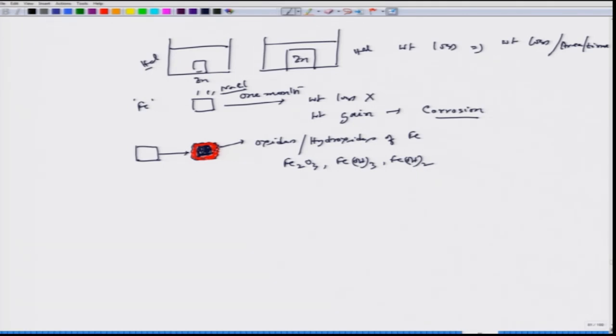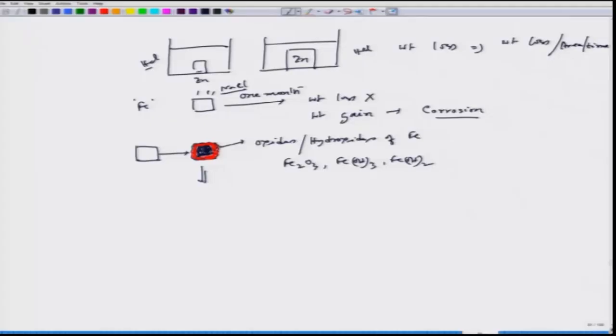In those cases, you have to carefully remove the oxide layer or the surface layer, and that removal should be done so carefully that the inner part, which is the metal part, should not get damaged or should not get removed. So that is what we have some standards, how to remove the oxide layer, which is mostly done chemically, and then after removal, we are left with this much small piece, and that one we have to take the weight. So this is W2 and here the weight was W1. Now, and this one is W prime. So W prime greater than W1, but W2 is less than W1.